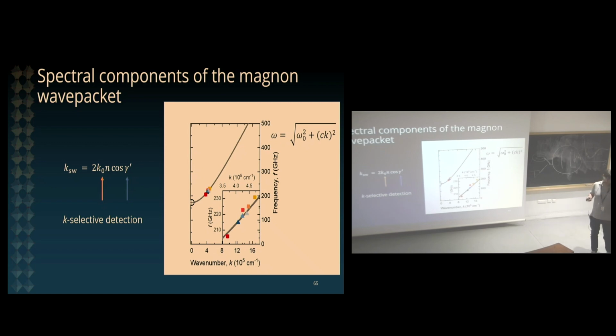And so we performed all the necessary checks, but in particular, what I found particularly important was to demonstrate that we can detect different components of this propagating wave packet. This can be varied by changing the geometry of your sample, so cosine of gamma prime here, and by changing k. Right. And so this is the result of our experiment. So these are different detections of propagating components of the wave packet performed in different experimental configurations. Those are the colored dots.